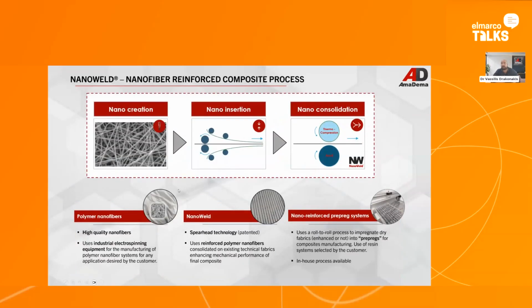Now, how do we do that? We actually have our NanoSpider that creates the nanofiber. We create the solution, and this is also something that we have worked a lot on, and we have done a lot of research in creating different solutions of different polymers. So we have, let's say, a pool of polymers and different nanoparticles for different applications. Then we do the nanofabric. On the next step, we insert the nanofabric on top and on the bottom of the main fabric under enhancement. So it can be carbon fiber, let's say, or glass fiber, or another aramid or bio-based, or name it basically, or filter media. And then we consolidate it with thermocompression and ultrasonic welding. There is a combination, we call it thermosonics.